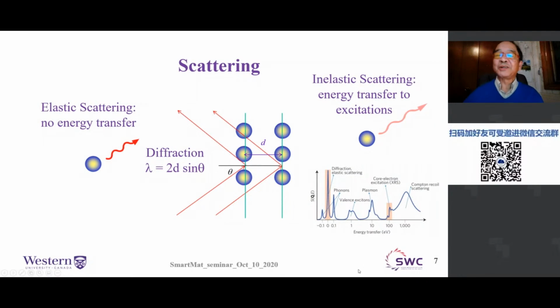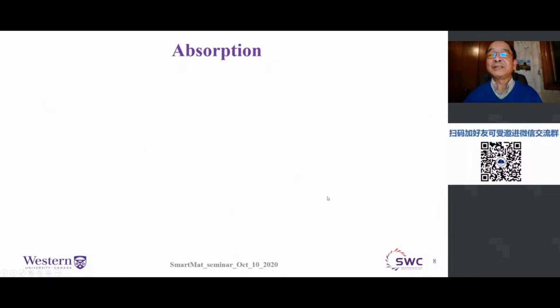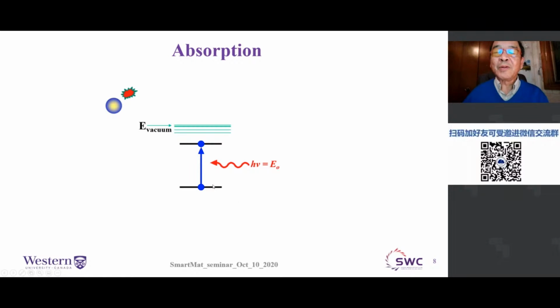But today, what I'm concentrating on is not scattering, but absorption. Absorption really is the most powerful tool for materials analysis. So what do I mean by absorption? Let's start with an atom. An impinging X-ray comes in. If the X-ray has sufficient energy to excite a core electron, then the X-ray is gone, the atom absorbs it. This absorption is normally a quantum transition from, say, the core electron to unoccupied states. In the case of an atom, of course, you have Rydberg transitions.